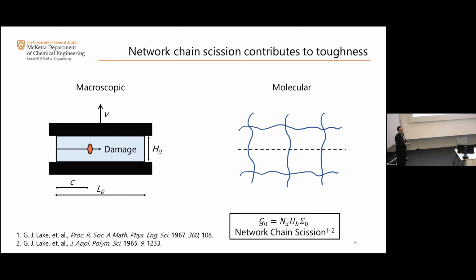So it's a minimum amount of energy that you have to pay in order to grow that crack. And basically, that's defined as this G0, the fatigue threshold that I was referring to before. And it scales with basically the chain length, or the number of monomers that you have in between the crosslinks, or the number of carbon-carbon bonds, the energy of each one of those bonds, which is this UB, and then this sigma 0, which is the density of chains that you would have in a fracture plane. Okay, so this is the Lake and Thomas picture.